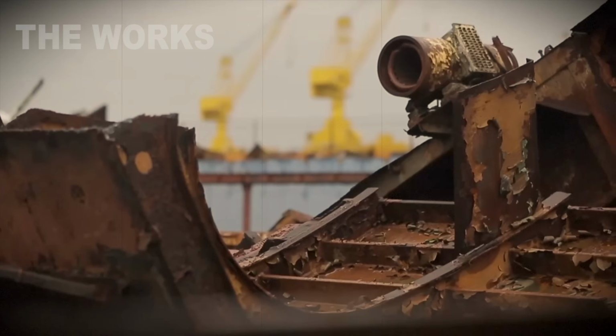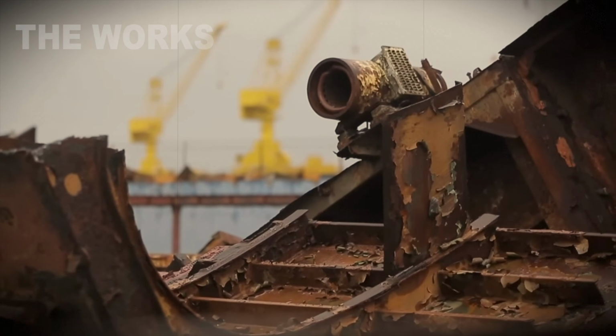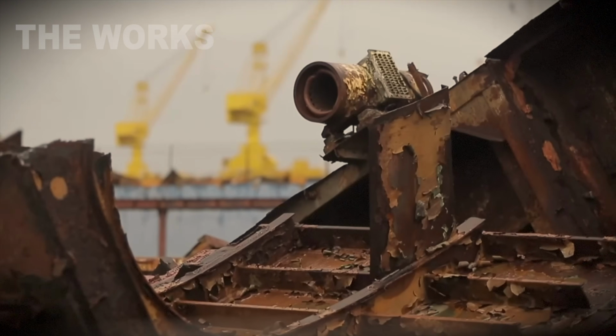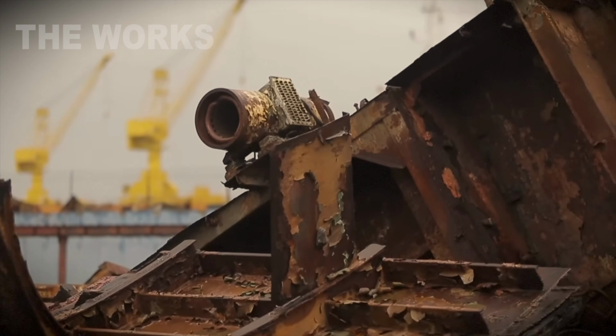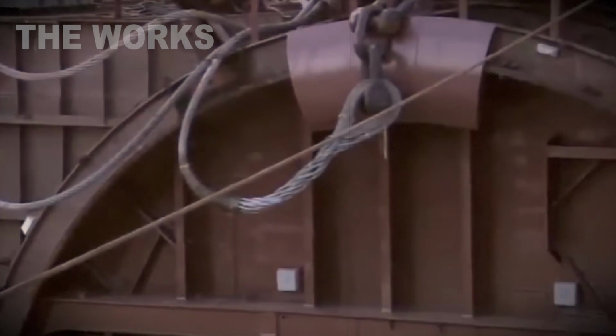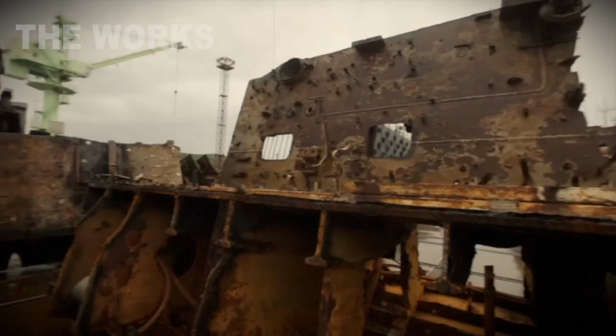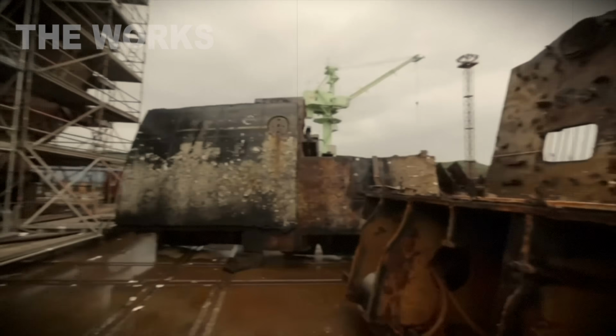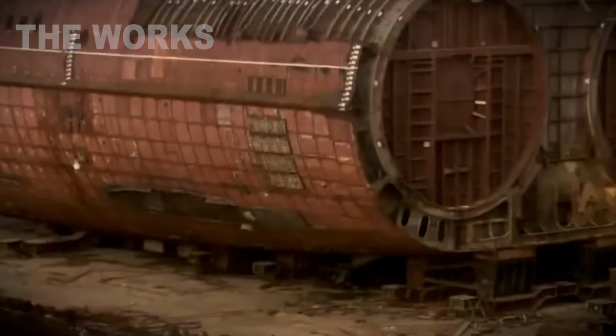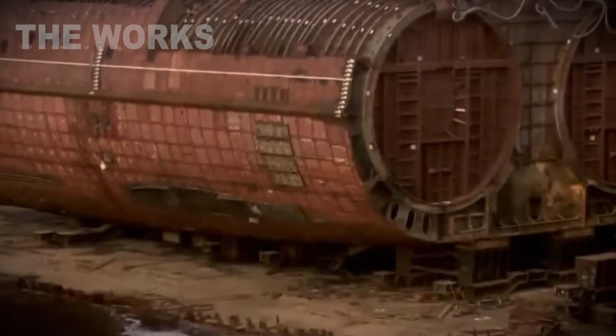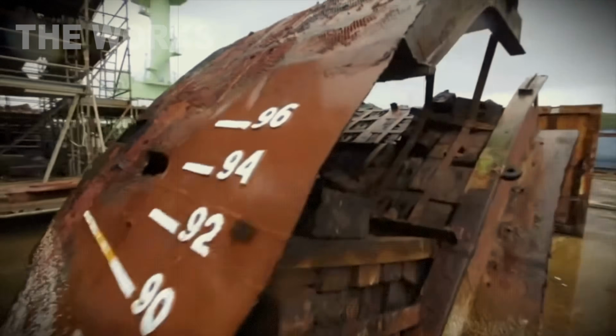The second tool, oxygen lances, a 10-foot steel pipe, 1-inch diameter. Inside, a bundle of steel rods, each about a sixth of an inch thick. Pure oxygen flows through the pipe at 150 psi. Flow rate, 50 cubic feet per minute. The rods are ignited with an acetylene torch. They start burning in the oxygen. Steel burns. Massive amounts of heat pour out. Temperature in the burn zone, 6,900 degrees Fahrenheit.